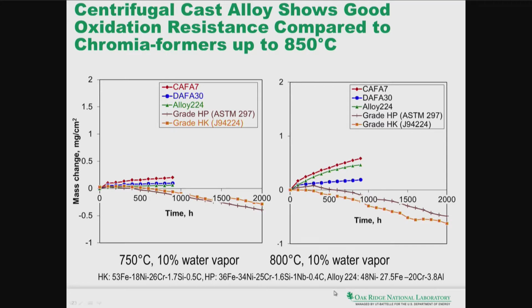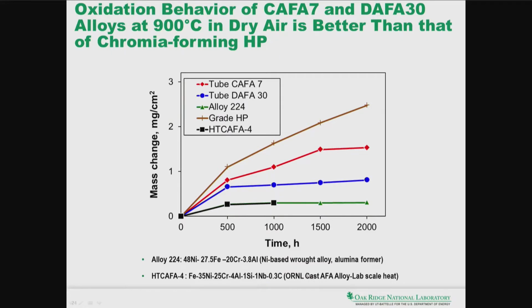Now going up to 900 C, we show data in dry air that is devoid of water vapor. Now you start seeing some more differentiation. The grade HP alloy, as you can see here, performs the worst amongst this group of alloys. Again, the CAFA 7 and the DAFA 30, the alumina-forming alloys developed by Oak Ridge, do well. And probably the best to target is alloy 224 under these conditions. What we also show here is a lab scale version of one of our alloys within the patent that starts to almost track the high nickel alloy.